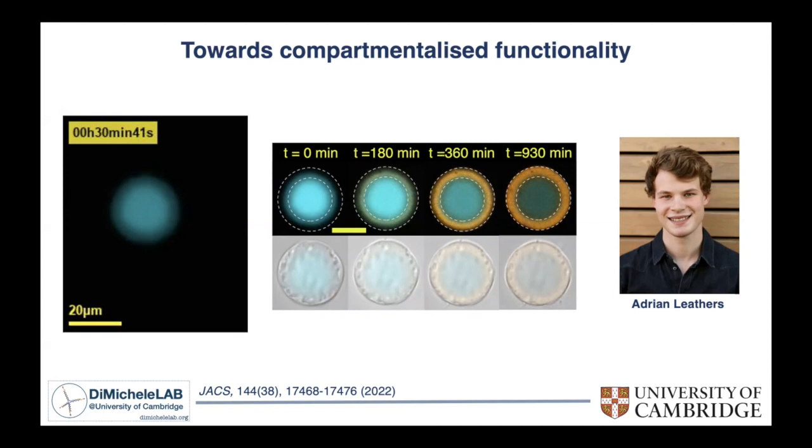And I think this is just because this is a very complex environment. Probably the template is twisted around this network of DNA, and the polymerase needs to make its way through. So I'm not surprised that it's slower, but it's significantly slower. Again, with the caveat that we don't know exactly how much of the template we have overall in these samples.